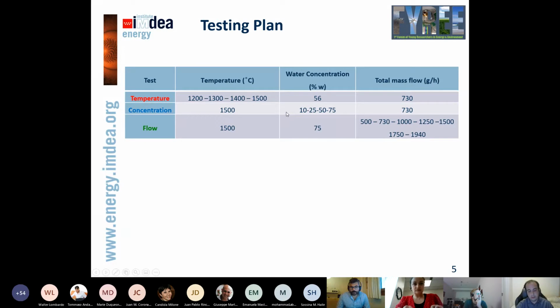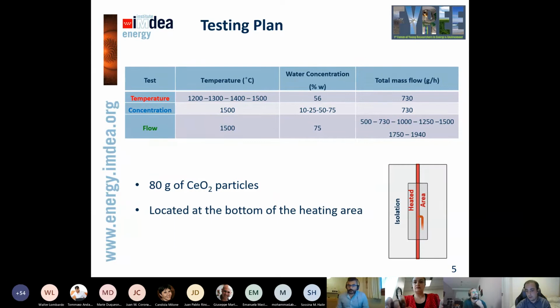Well, and how are we testing? Basically, what we did was we chose 3 key parameters: temperature, the water concentration that we inject, and the total mass flow rate. And we just switched one by one, maintaining the other 2 constant for several tests. All tests were run more or less under the same conditions, in which we just get around 80 grams of ceria particles inside the reactor. And as I said before, they're just located at the bottom part, to try to get most of the water evaporated by the time it reaches the reactor.